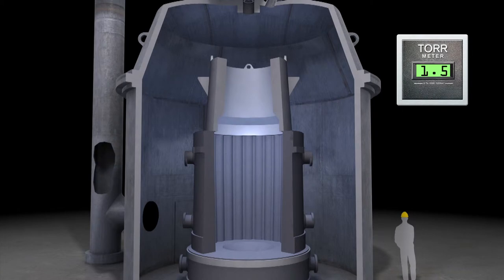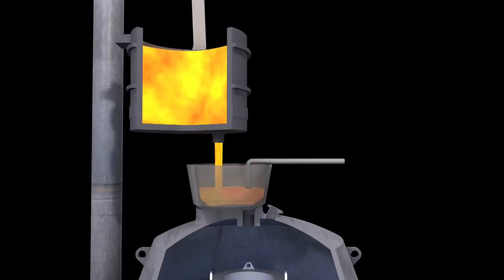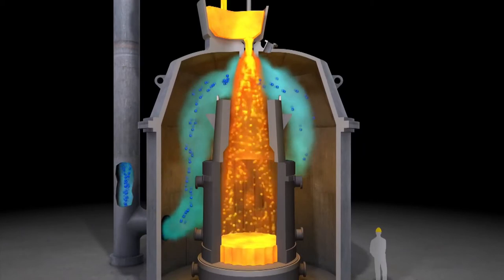After the drying, the pressure in the vacuum tank is reduced below one torr. The furnace ladle then begins filling up the pony ladle with molten steel. Once the pony ladle is filled, its stopper valve is opened, allowing the flow of molten steel into the vacuum tank.